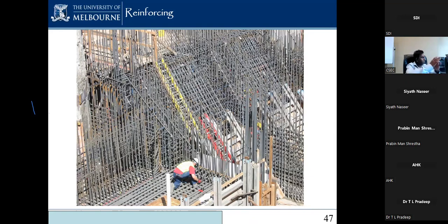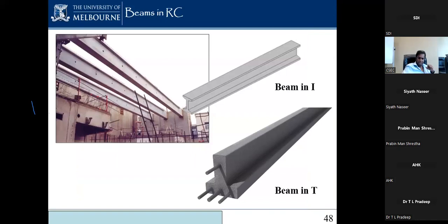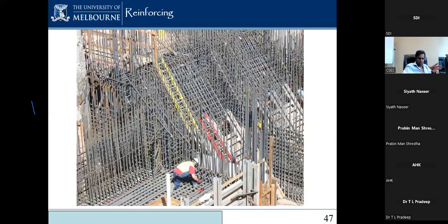What happens is sometimes your reinforcing bars are too close to each other. Because of that, the concrete can't go in. The rule of thumb that we normally use is that the distance between the centers of reinforcement should be more than 3 times the diameter. The aggregates also have to pass through between the reinforcement.